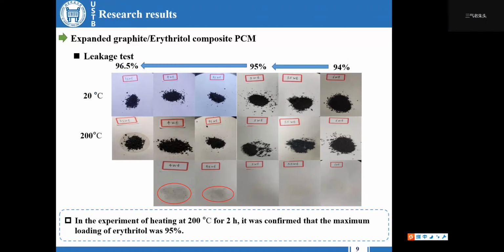Through leakage experiments to determine the maximum loading of phase-changing materials, 6 samples with different phase-changing material loadings were heated at 200 degrees for 2 hours. The maximum loading of erythritol was determined to be 95%, and the addition of expanded graphite was 5%.